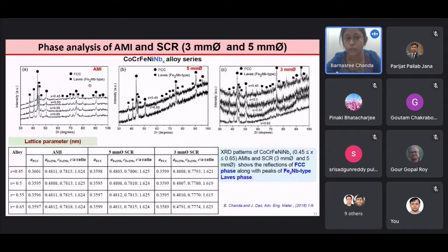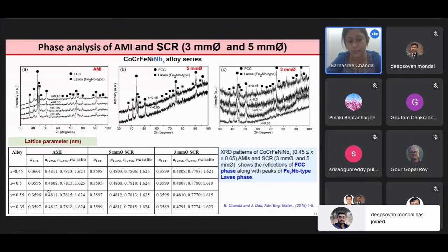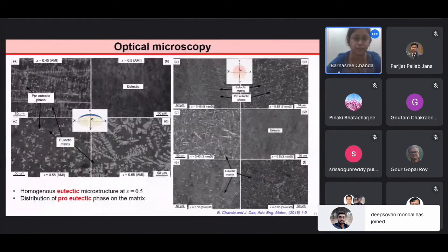Phase analysis of arc melted ingot and suction casted rod. First, the alloy series cobalt chromium iron nickel niobium. Figure A, B, C shows the XRD patterns of the alloys developed by different solidification processes, where we see the reflections of FCC and Laves irrespective of the alloy development process. Also, a very insignificant difference in the lattice parameter has been observed.